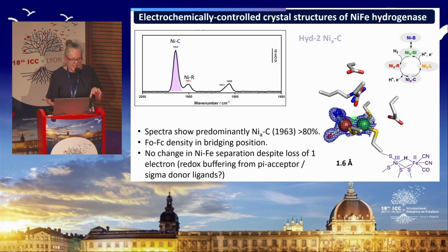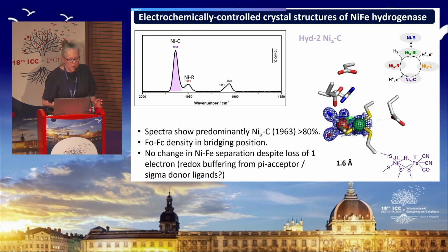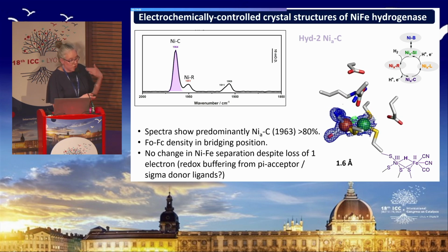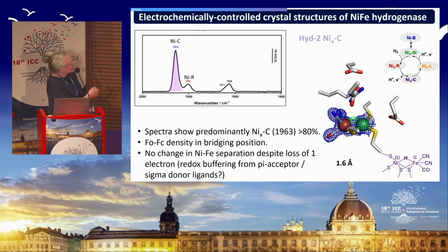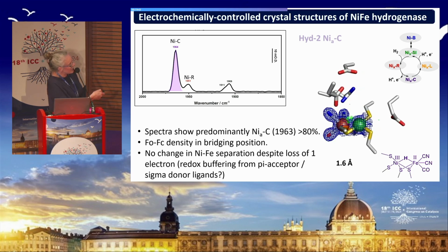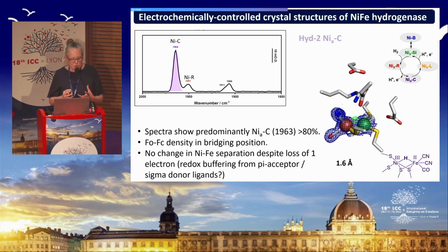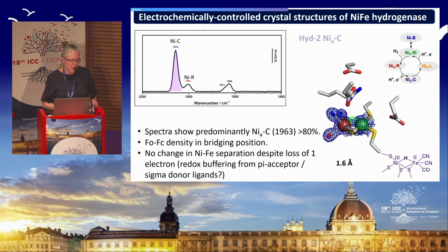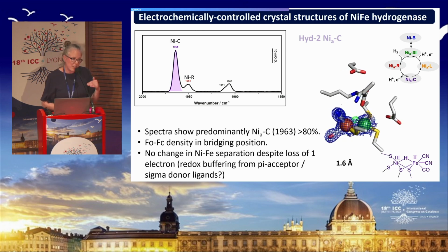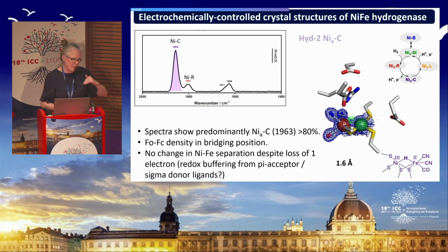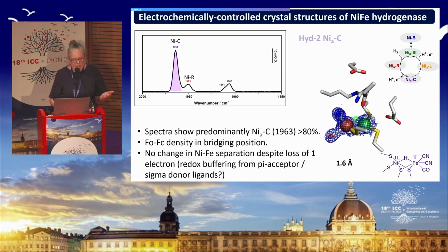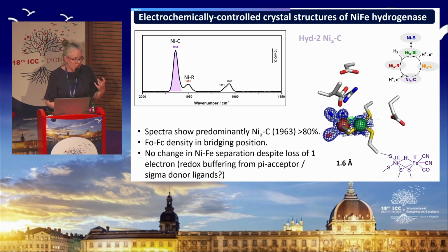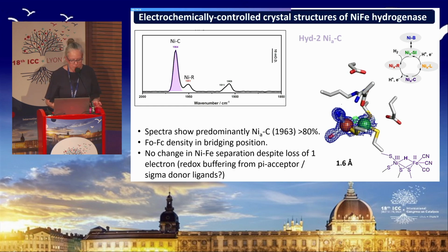We then move around the catalytic cycle to the nickel C state, where we have now gone to a nickel 3 state, so the nickel's oxidized, and we maintain the hydride bridge as we expect. And interestingly, the metal-metal distance has not changed at all in these structures, despite the loss of an electron from the active site. I think that really shows the impact of the redox buffering of the combination of pi acceptor sigma donor ligands for the CO and cyanide on the active site, which allows you to add a whole electron without actually moving the metal distances at all. And so this is an incredibly rigid catalytic site.